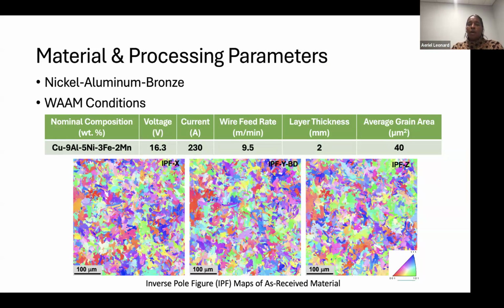If you ask me about the WAAM conditions, I can't tell you too much about it because we get these made by a company called Gefertec, a German-based company that has pretty much perfected the printing process of nickel aluminum bronze. But this is what the as-received material looks like. It has a grain area of about 40 microns squared.